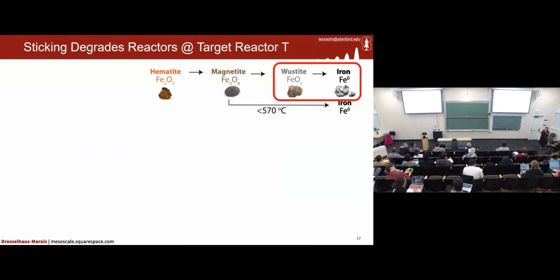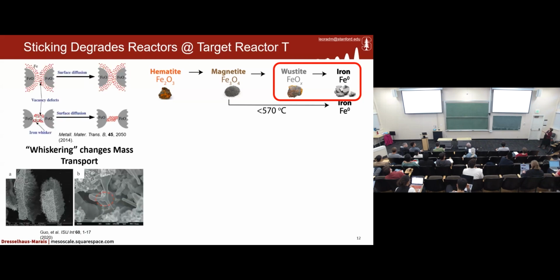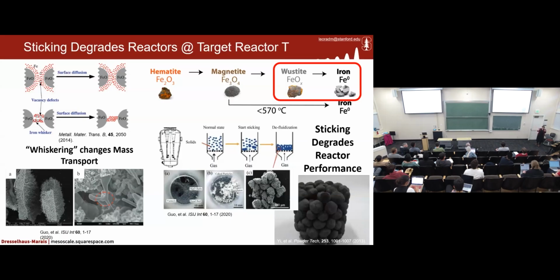So beyond just the chemistry being challenging, it's important to understand that actually one of the big challenges here is scaling up the problem. Because this last step here is not as trivial as you might think. This last step here actually creates a really sticky thing called wüstite, which causes all of the iron particles to start to stick together. So ultimately, it creates what's called whiskering, where the pellets form these iron little whiskers that float across and stick together, causing now the entire thing to turn into all of these pellets in just this stuck little category. So now, instead of having continuous flow of our reactors, we have a stuck reactor that has to stop, and millions of dollars have to be spent on carving out all of the iron that got stuck to the reactor vessels.